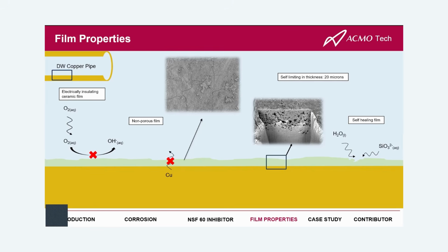And in the case that the film is damaged by debris or flowing water through erosion, thankfully, this film is self-healing. So this program is a continuous treatment program. And so any silica that sees a defect is going to go and bind, and it's going to fill up that defect, protecting all of your domestic piping from corrosion.